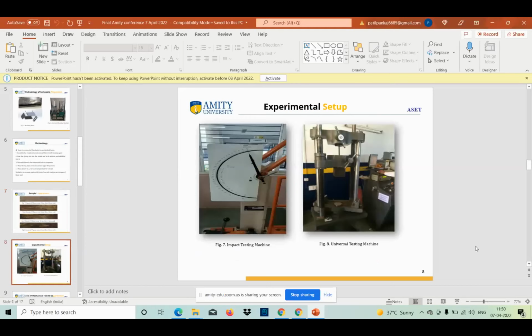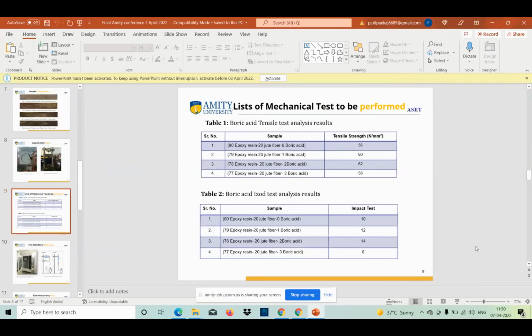Using that, we will prepare the samples for testing using an injection molding machine. After that, we will test the samples using the impact testing machine and the universal testing machine. Using these machines, we will analyze the sample with 78% epoxy resin, 20% jute fiber, and 2% boric acid. The tensile strength increases in that sample, to 62 Newton per mm square.